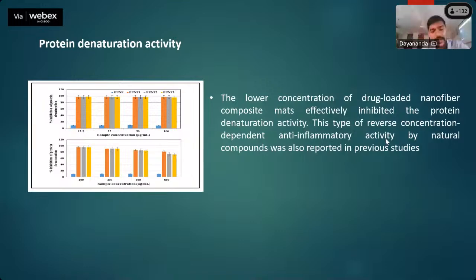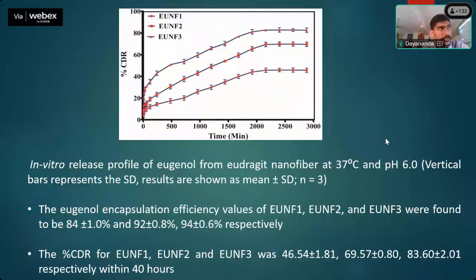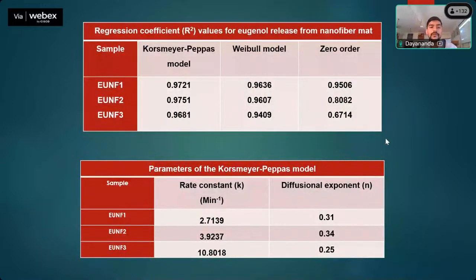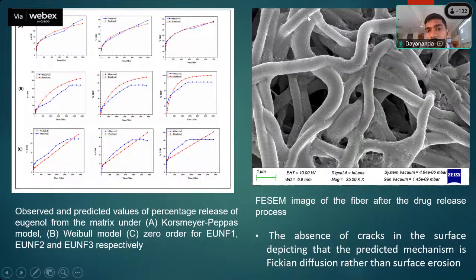Since we had fabricated 3 different nanofiber mats, the encapsulation is different, and the cumulative drug release is also different from different nanofiber mats. It was fit with various kinetic models and found to fit well with the Korsmeyer-Peppas model. The diffusional exponent was found to be 0.34, 0.25, suggesting that release of the drug or loaded compound from the mat occurs through a diffusion process.